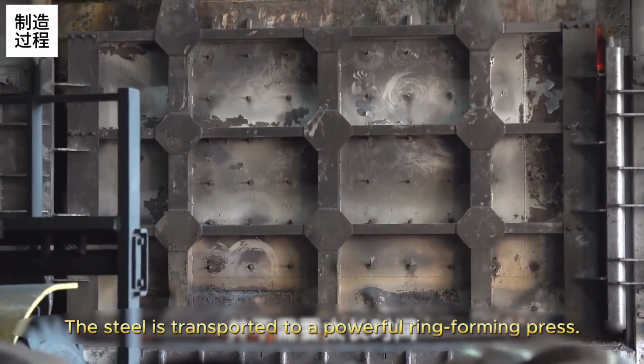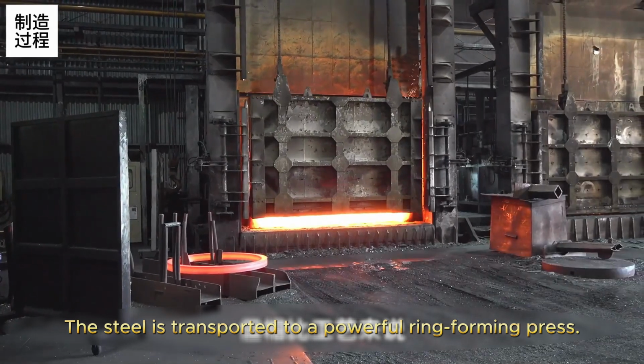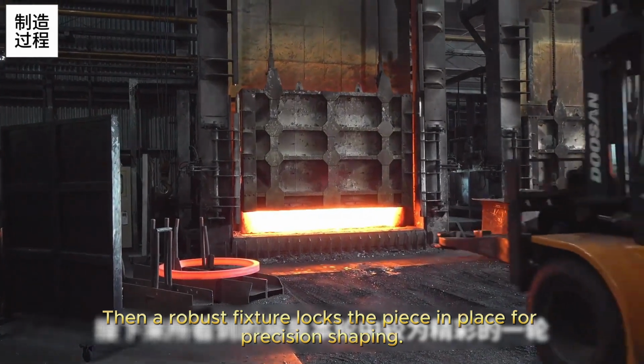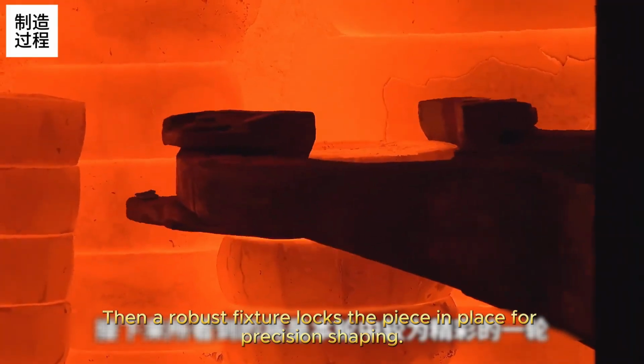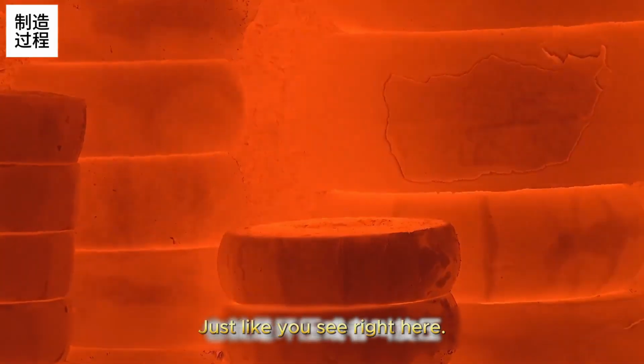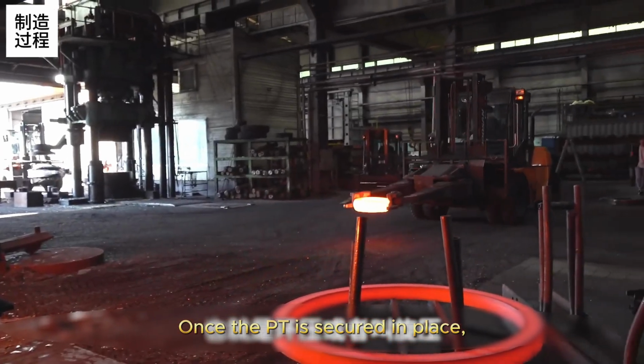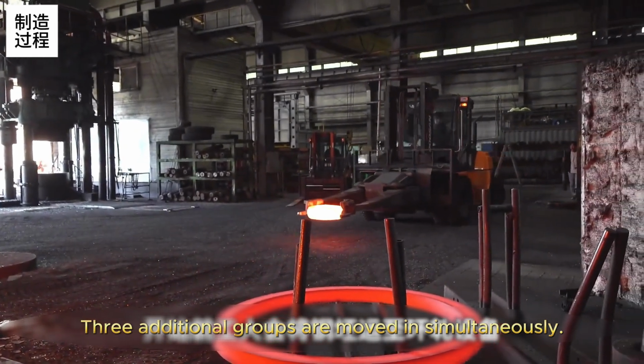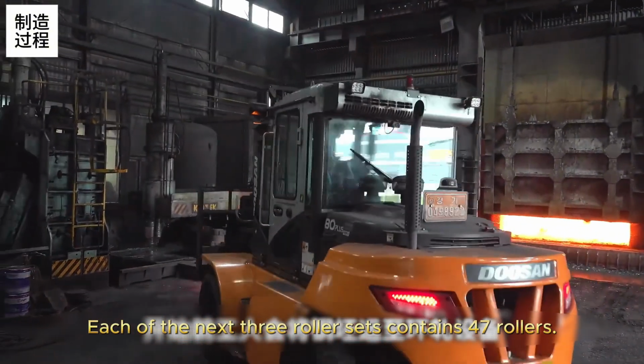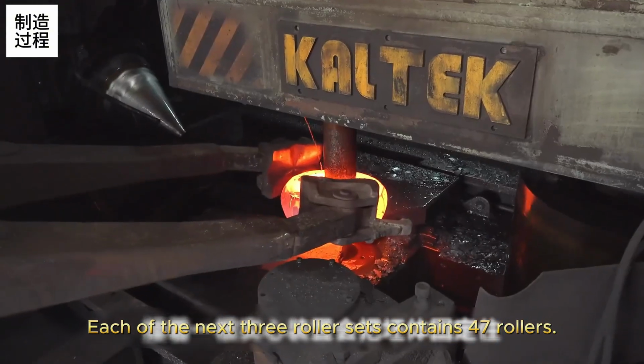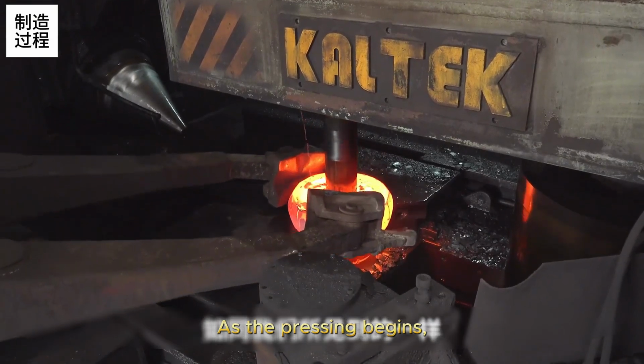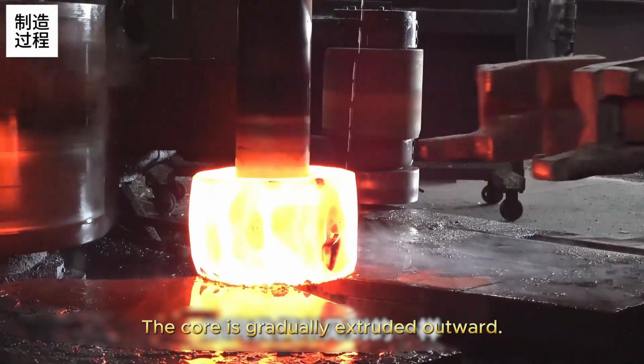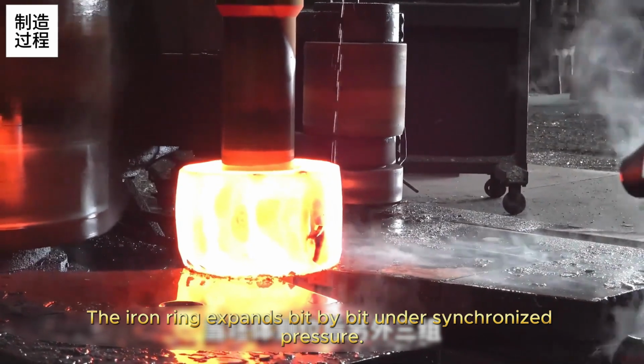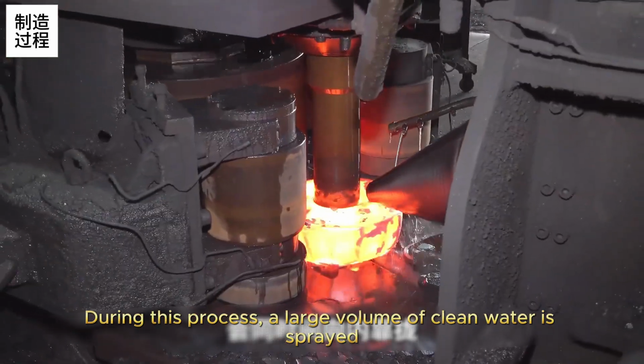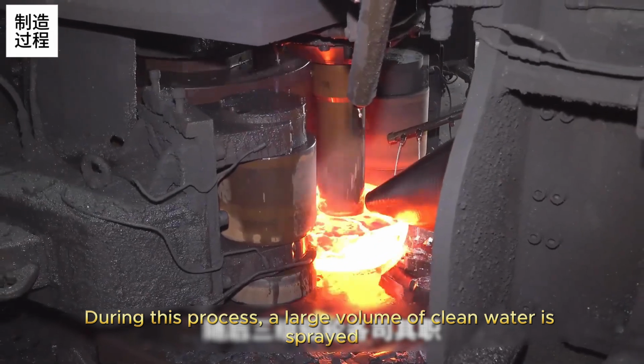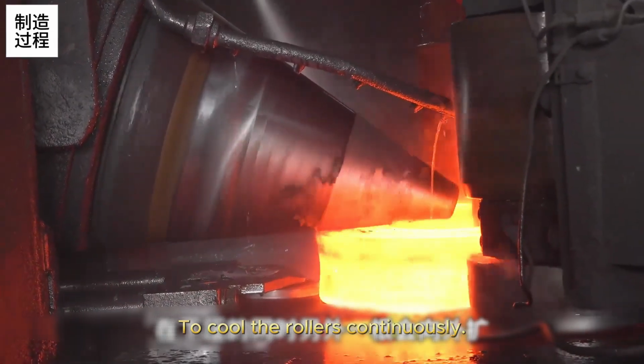Before it begins, the steel is transported to a powerful ring-forming press. Then a robust fixture locks the piece in place for precision shaping. Just like you see right here, once the piece is secured in place, 3 additional groups are moved in simultaneously. Each of the next 3 roller sets contains 47 rollers. As the pressing begins, the core is gradually extruded outward. The iron ring expands bit by bit under synchronized pressure. During this process, a large volume of clean water is sprayed to cool the rollers continuously.